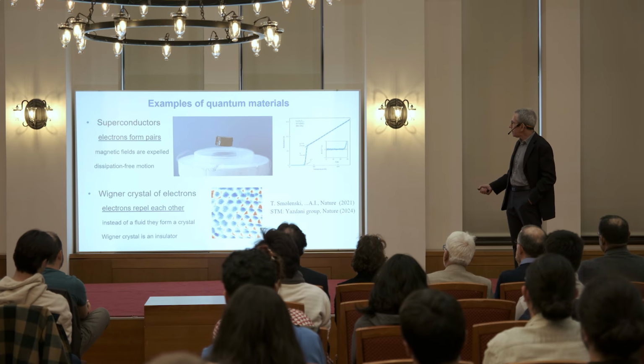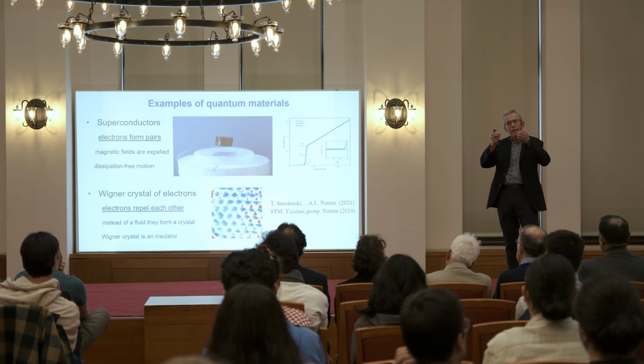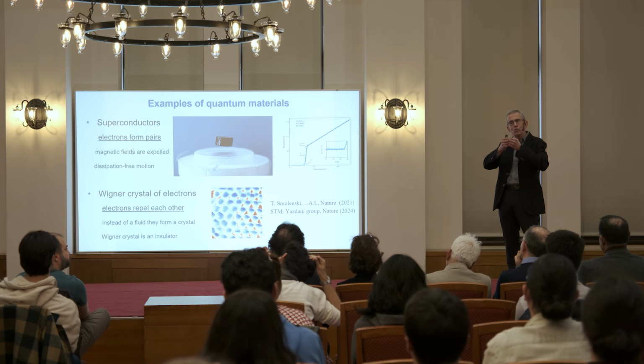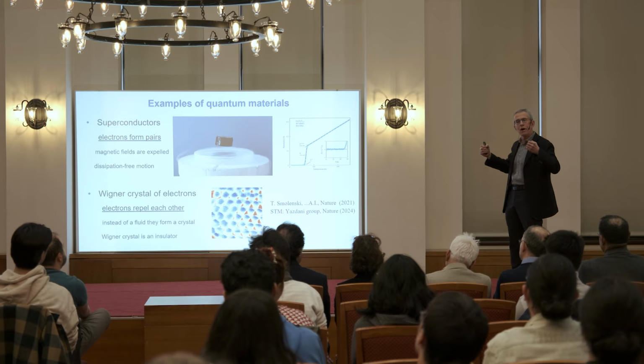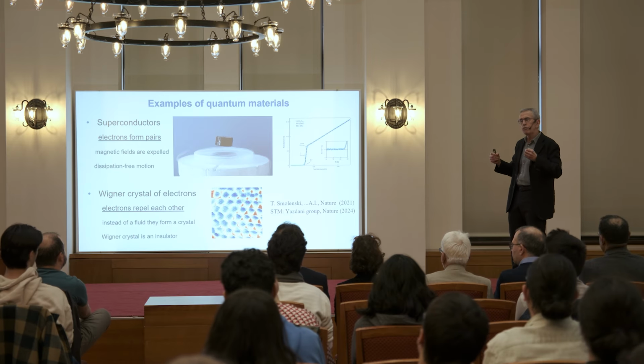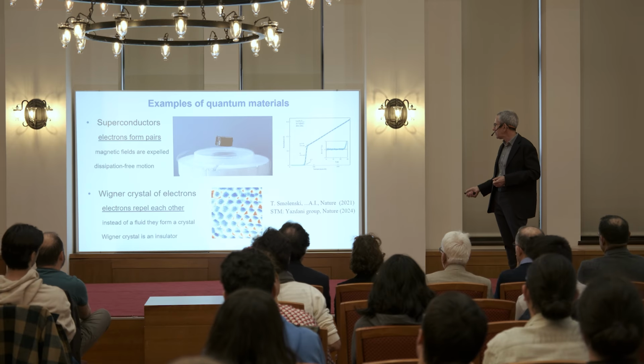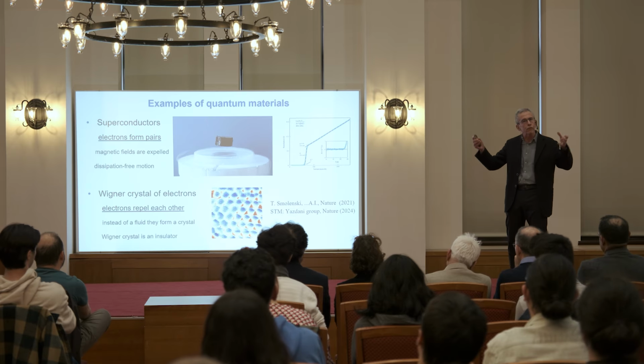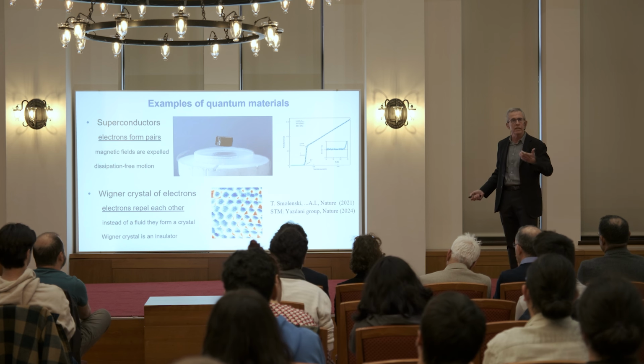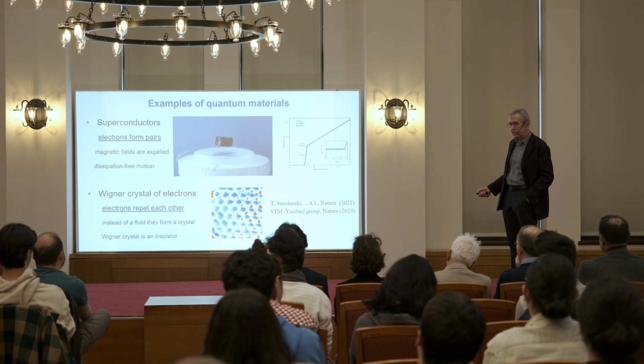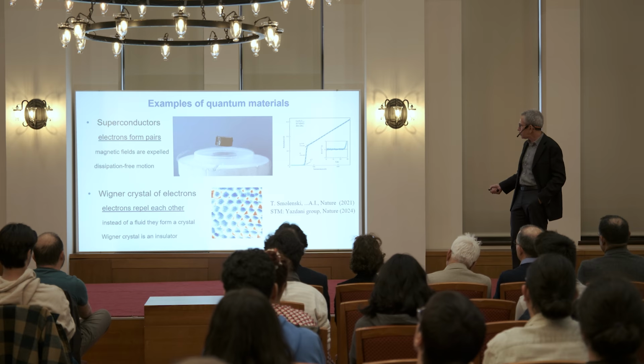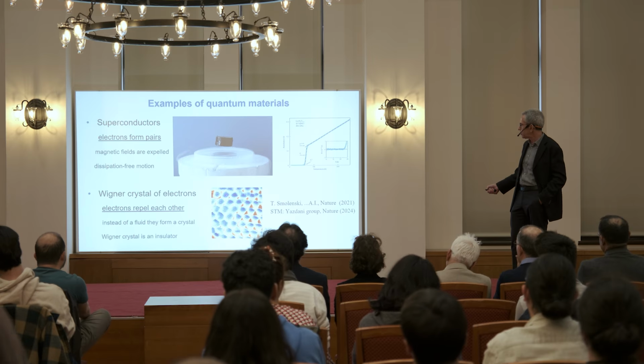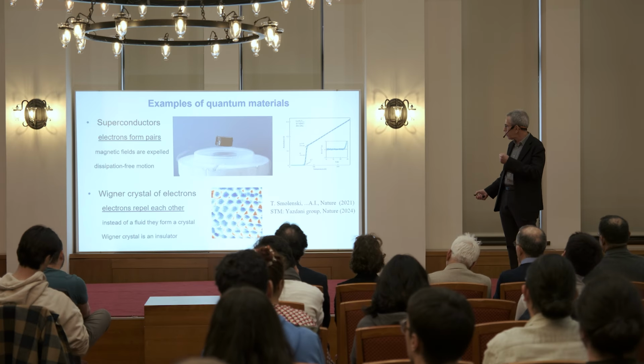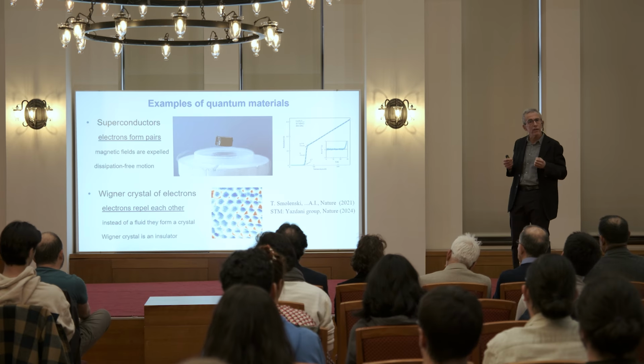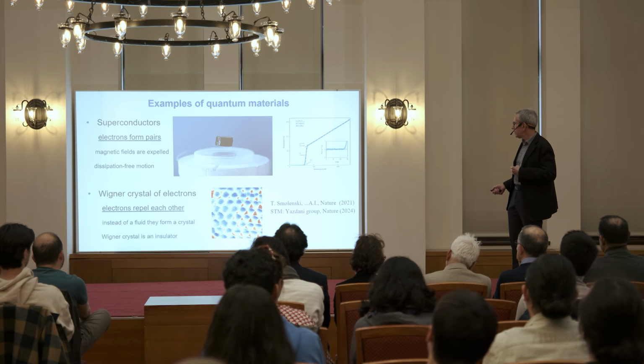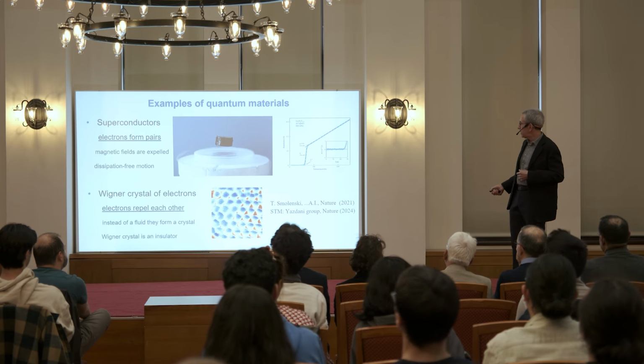Okay. And then the other extreme is not when electrons effectively attract each other, but in the limit when electrons really dislike each other so much that the best way for them to minimize the repulsion is to crystallize. So instead of forming a fluid, as is the case in more traditional materials like metals and semiconductors, in this case, they actually crystallize to maximize the distance between them. Okay, so these blue spots are where electrons are. They form a triangular crystal in a two-dimensional material, and they become insulating, a very good insulator.